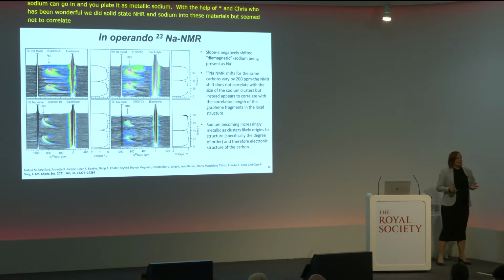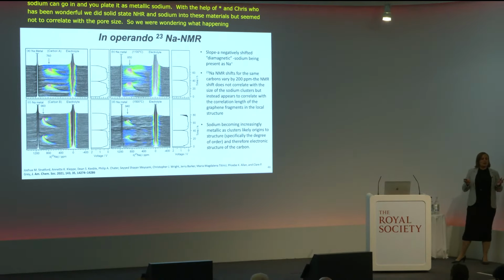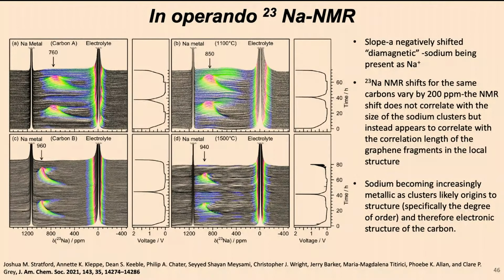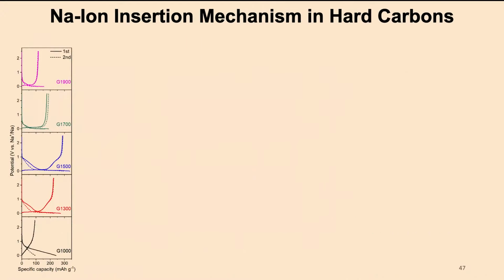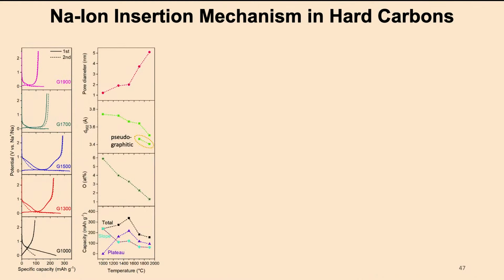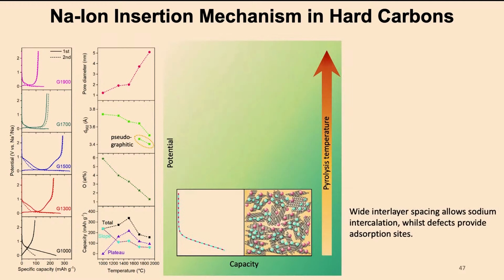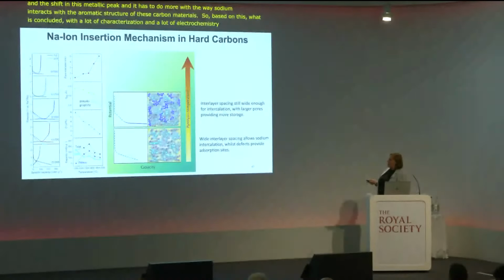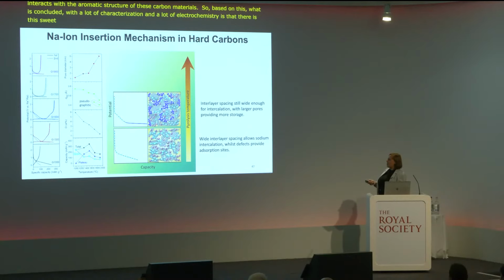Anyway, we did some more NMR, and we figured out there is actually no connection between the pore size of our carbon materials and the shift in this metallic peak. It has more to do with the way sodium interacts with the aromatic structure of these carbon materials. Based on this, with a lot of characterization and electrochemistry, we've concluded that there is a sweet spot where the interlayer spacing is large enough for sodium to sit as metallic sodium in these pores, and that's where we store more sodium.